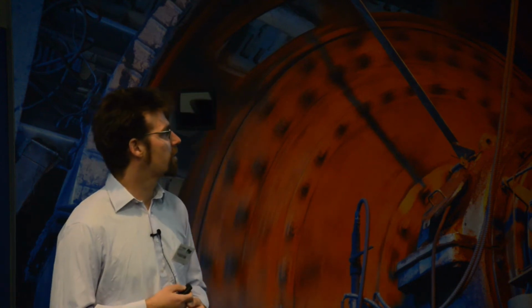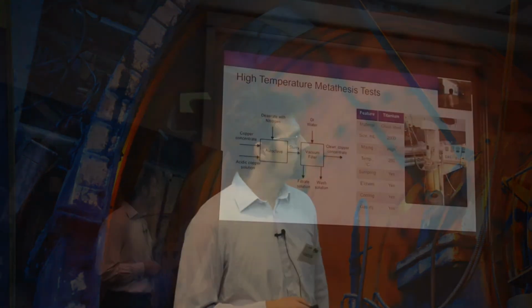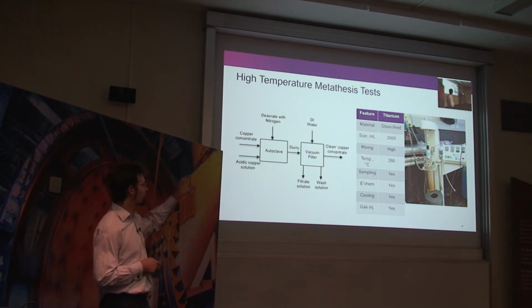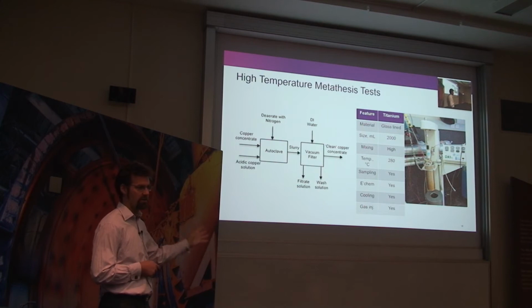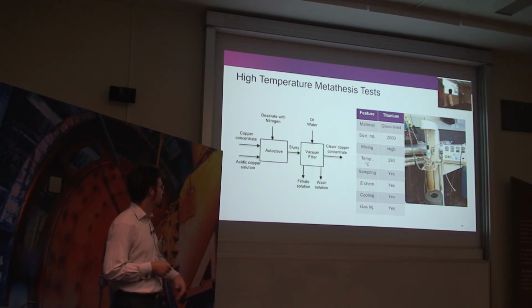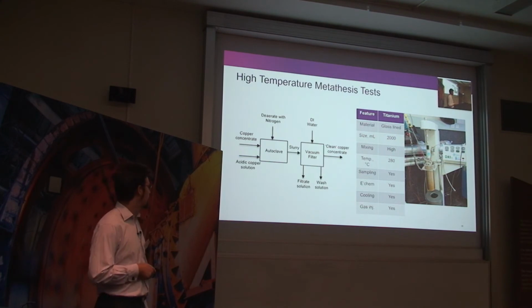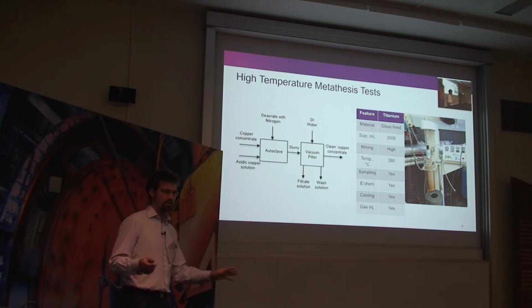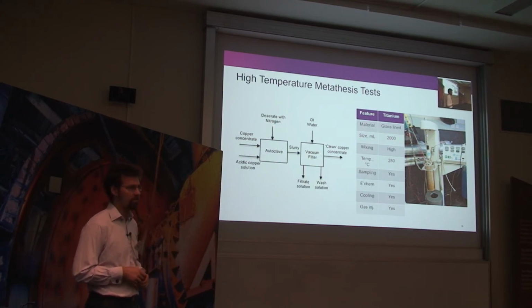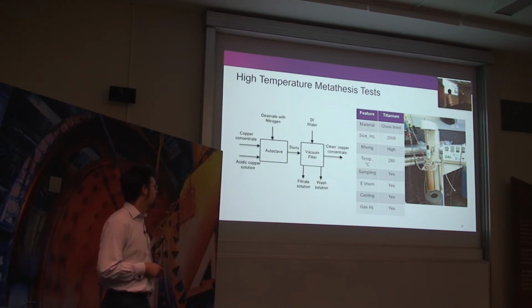of the experimental studies that were done here. So this is for the high temperature metathesis experiment, the batch autoclave experiments, where we put in a copper concentrate and an acidic solution. We started off by deaerating with nitrogen to exclude any external oxidation. We run the autoclave at set temperature for set time. Baseline conditions are 200 degrees for 1 hour.